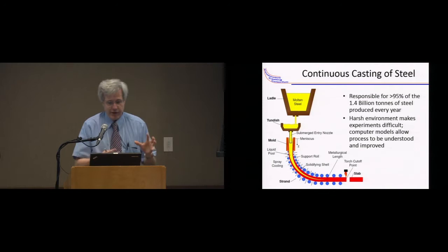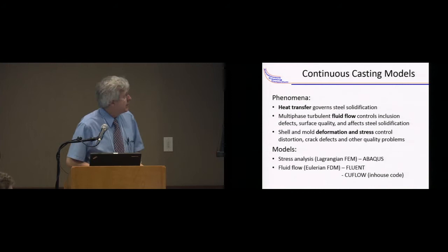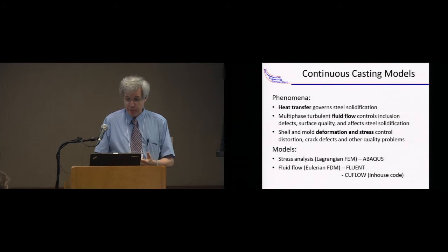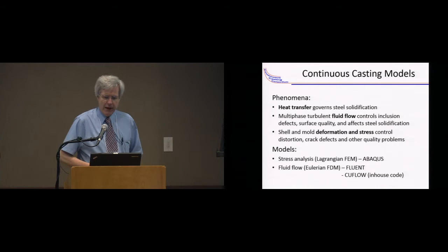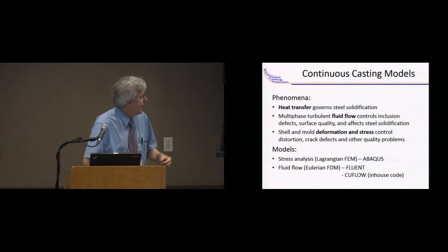So some of the phenomena that we're worried about is heat transfer. Obviously, that governs solidification. We've got multi-phase turbulent fluid flow. This governs the formation of inclusions. There's gas injected, argon, in order to control the flow and prevent clogging problems. We've then got deformation and stress of this shell, crack problems, and there's things in the microstructure. So there's a lot of phenomena.